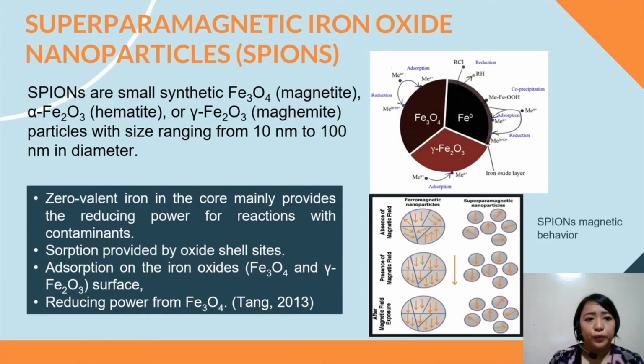Another research I'm doing is the synthesis of superparamagnetic iron oxide nanoparticles, or SPIONs, from black sand. So SPIONs are small synthetic magnetite, hematite, and maghemite particles with size ranging from 10 nanometers to 100 nanometers in diameter. What happens is when we apply an external magnetic field, it allows the particles to achieve their saturation magnetization and exhibit no residual magnetic interaction once the applied magnetic field is removed.